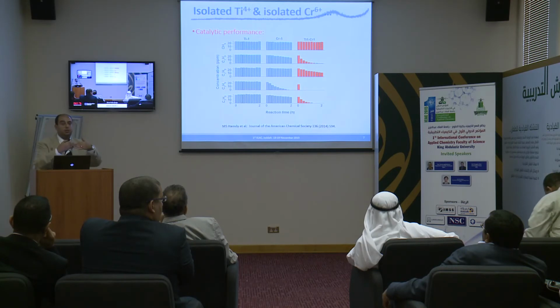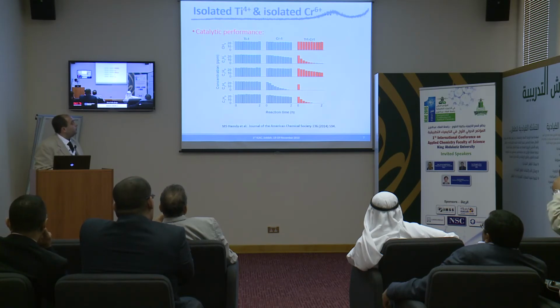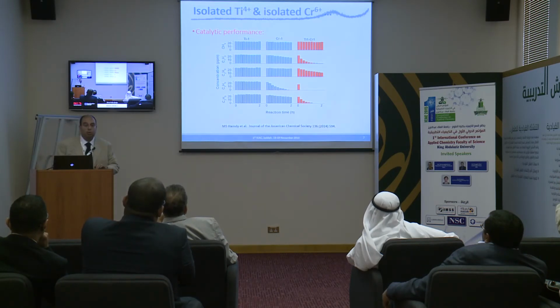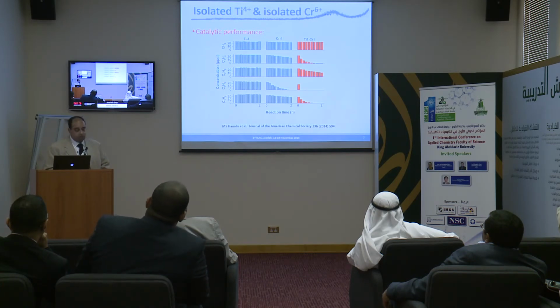However, if you combine these 2 together, so you have your titanium and your chromium, this is the result that you will get. Methane is quite actually a stubborn molecule to be degraded, but you can fully degrade 3 of the 5 gases within 2 hours. So almost 75 ppm of your gases has been totally gone within a couple of hours. And this actually was reported last year in JACS.